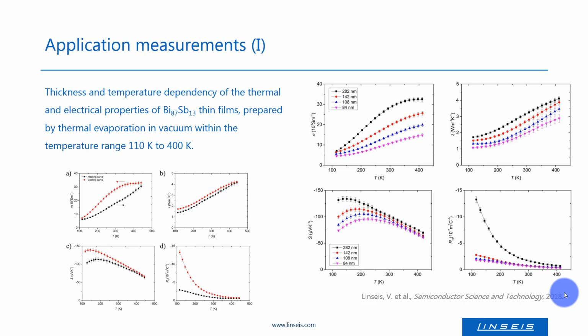With the next two slides, some remarkable measurements are presented which were done with this platform. The first one was a typical thermoelectric sample, bismuth antimony, where strong size effects were shown, which impact all transport properties, thermal and electrical. Both have been heavily affected.